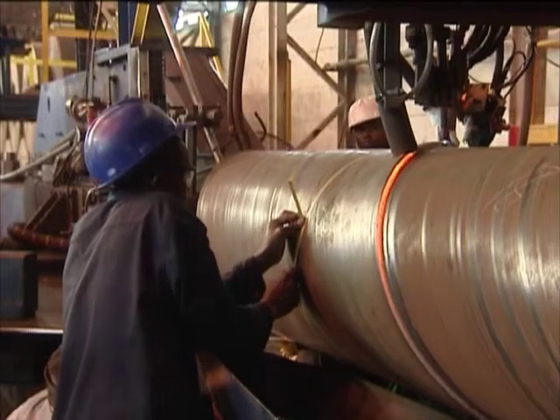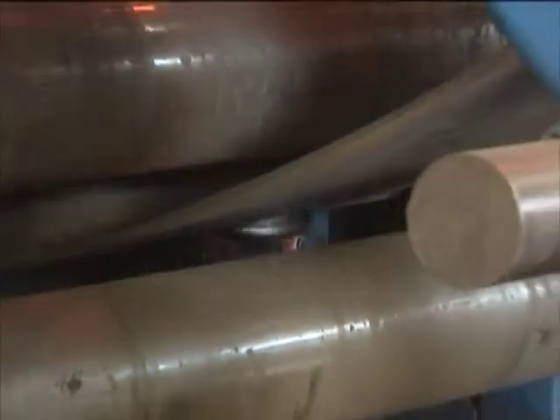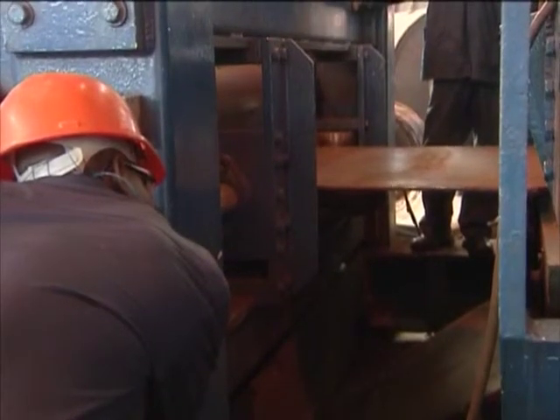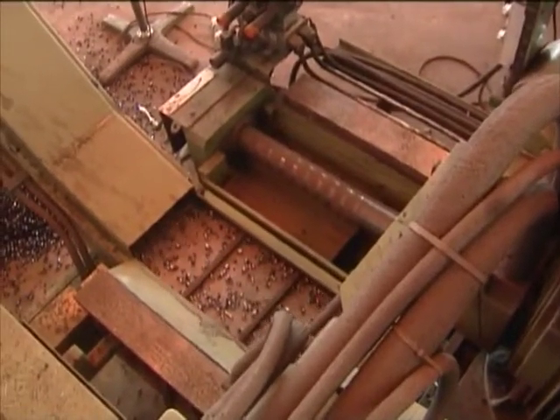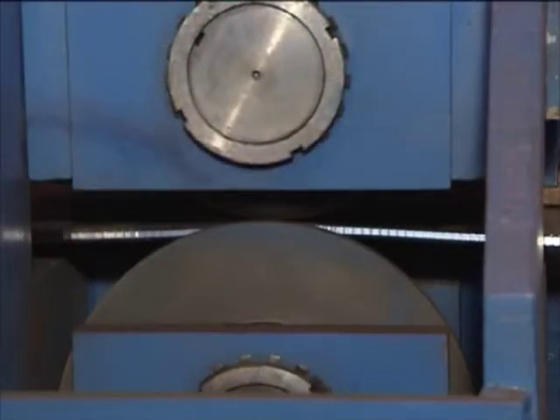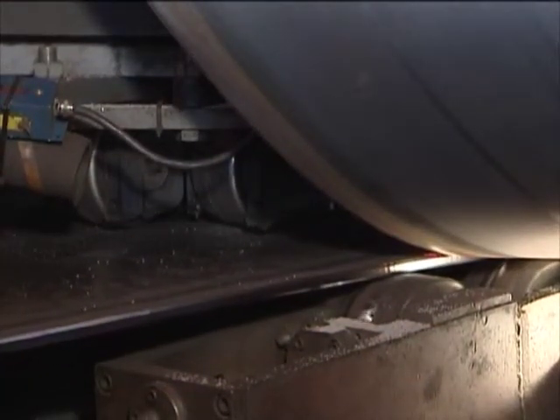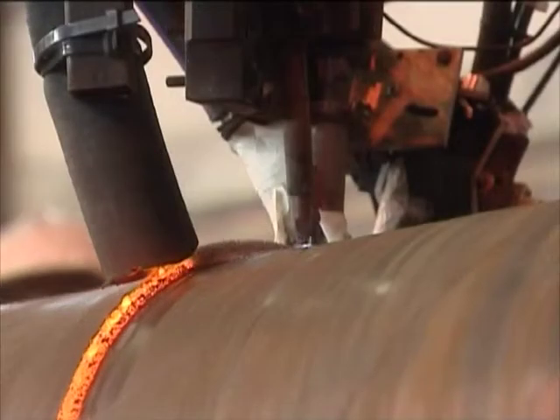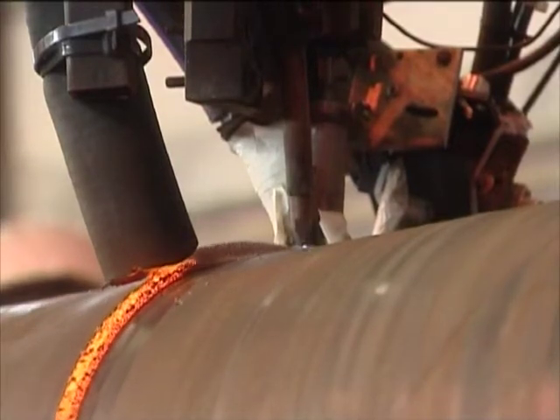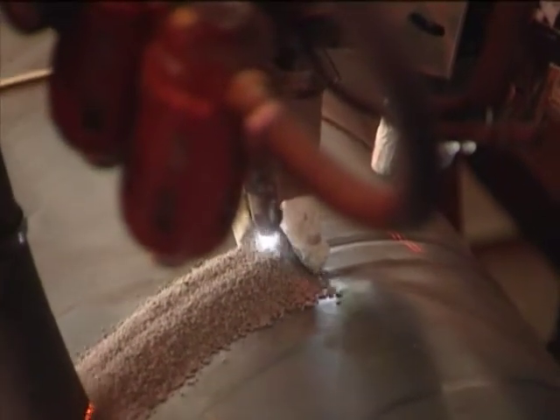SCC's ultra-modern pipe mill uses the helical-formed double-submerged arc welding process. The hot-rolled steel strip passes an edge milling unit where the plate is milled to the required width and the edge is prepared for the welding process. The plate then passes through an edge preform section where the edges are formed to ensure an accurate edge alignment and pipe shape. The pipe is then helically formed with an orbital moving 3-roll bank of accurately shaped rollers. 4 electronically controlled welding heads perform welding inside-out simultaneously to create a weld seam much stronger than the parent metal. The weld seam tracking and weld gap are controlled by electronic laser beam technology and ensures real-time consistent weld bead positioning and on-seam welding.